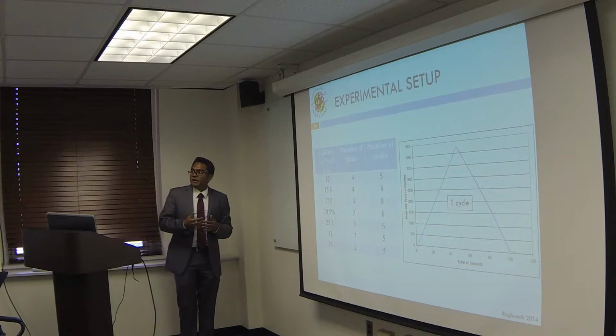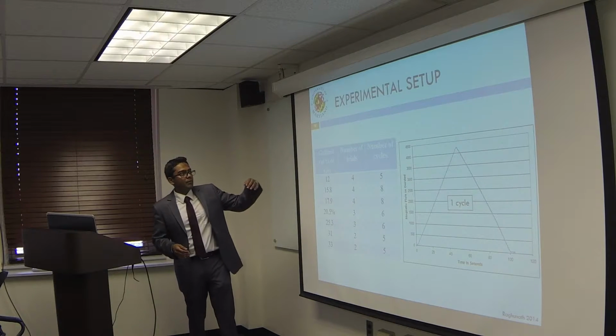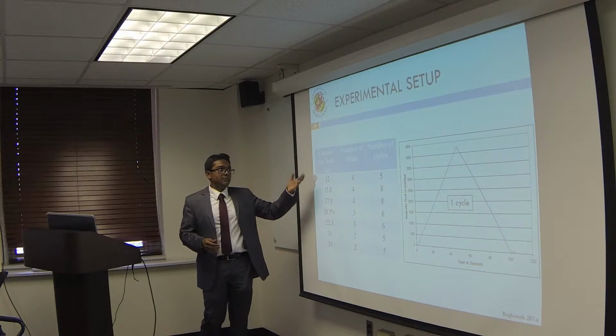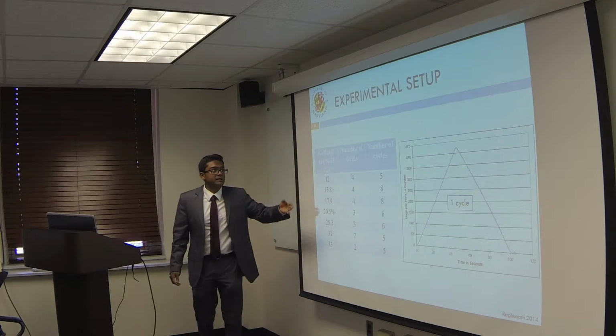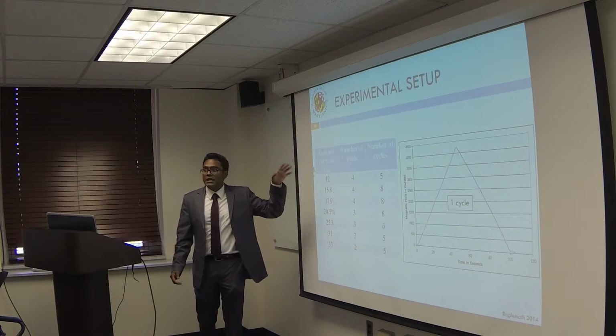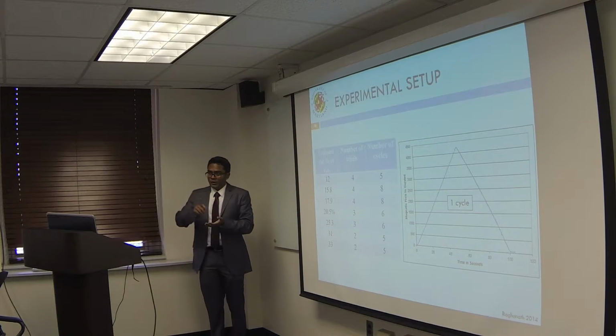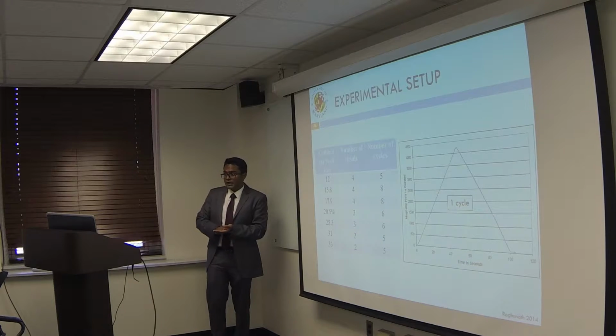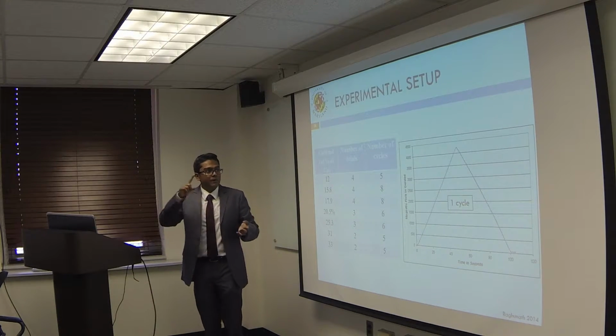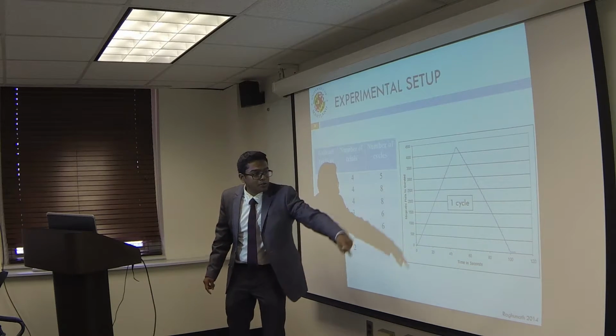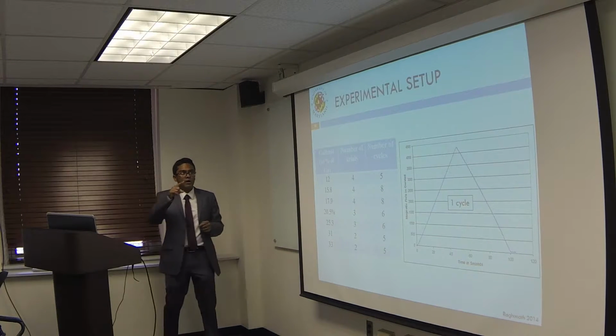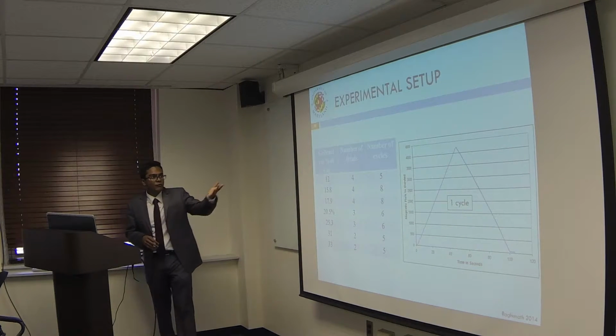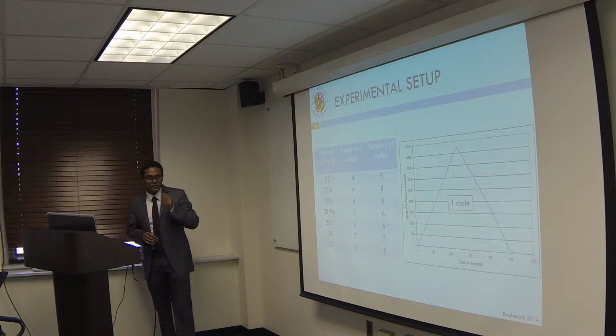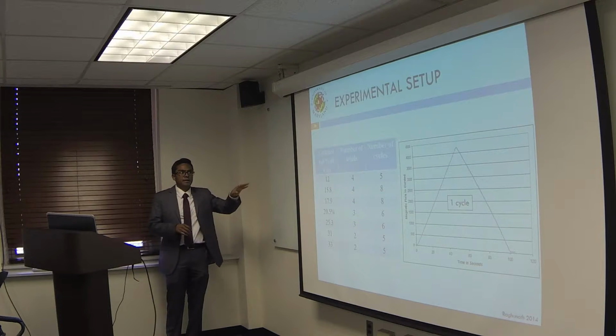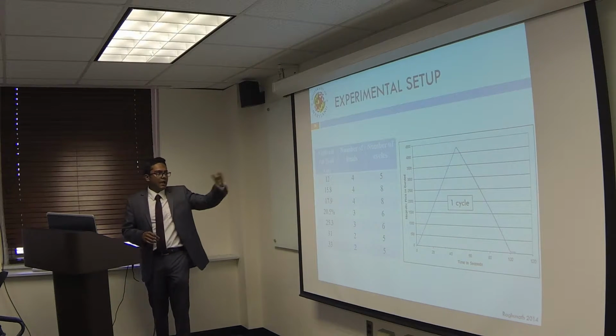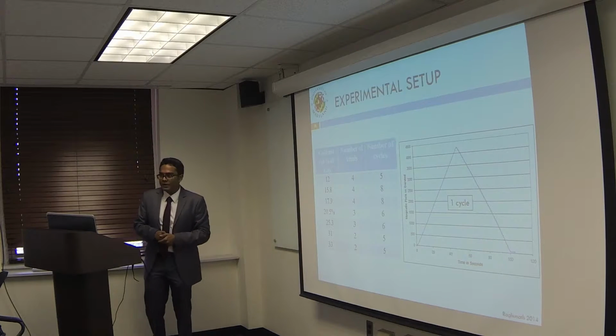For repeatability purposes, I decided to perform the experiment over multiple trials and over multiple cycles. Each trial involved taking off the strain gauge and putting on a new strain gauge, and each cycle was ramping up and down. So this corresponds to 1 cycle where I went up to 400 millitesla or 4,000 Oersted, and then back down to 0, and that's 1 cycle. I did at least 5 cycles for each sample, and at least 2 trials for each sample.